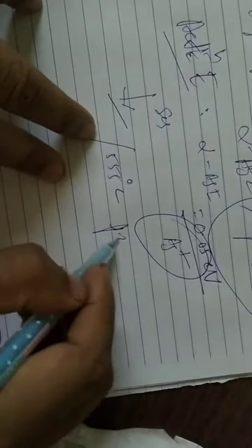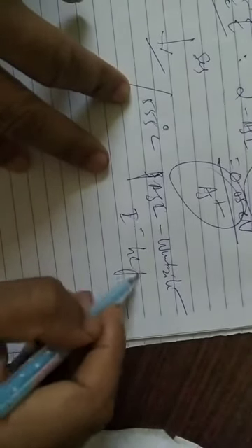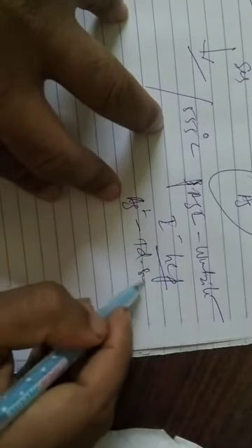Beta AgI has the wurtzite structure, with iodide, I minus, ions in a hexagonal close packed arrangement. Here the Ag plus ions can move towards the tetrahedral sites. And alpha AgI is BCC.